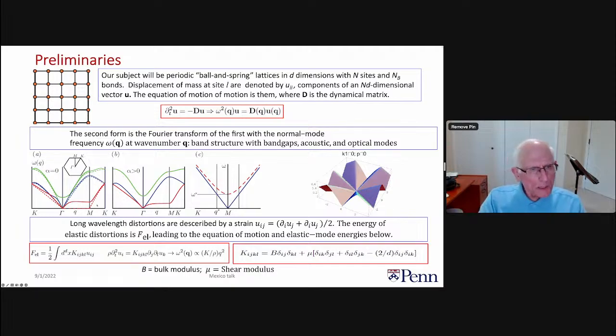Now, if I turn on a next nearest neighbor force, then you get this other pattern in which the zero mode has disappeared altogether, and I have only the two red lines right here, which are the two acoustic phonon modes hitting zero at gamma. And then up here, I have band gaps of various kinds. Now, the same thing happens when I go back here just quickly.